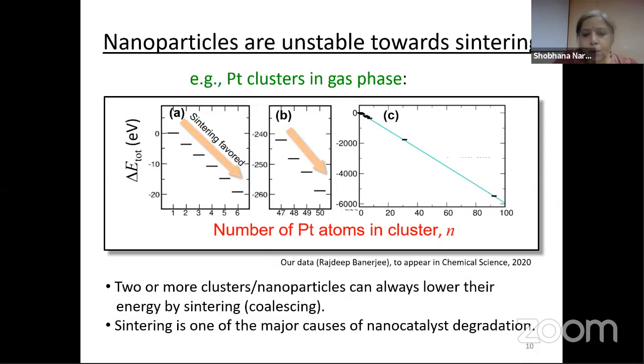However, there is one problem, which is that these very small nanoparticles are unstable to what is called sintering. Smaller particles are not energetically stable. They can always reduce their energy by coming together and forming larger particles. So here I've shown, for example, for platinum, that if you increase the number of atoms in a platinum cluster, the energy is always lowered.